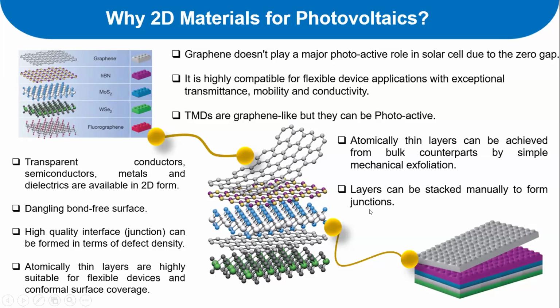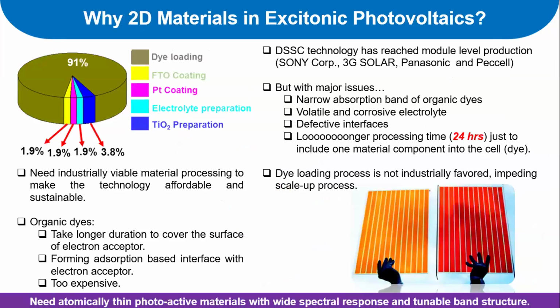So the major advantage of these 2D layered materials for photovoltaic applications is their dangling-bond-free surface. Once we remove one particular layer, the materials are free from dangling bonds, so in principle they don't have surface defects. The defect density is extremely low compared to other categories of material. And they are atomically thin, so they are highly flexible and highly suitable for flexible devices.